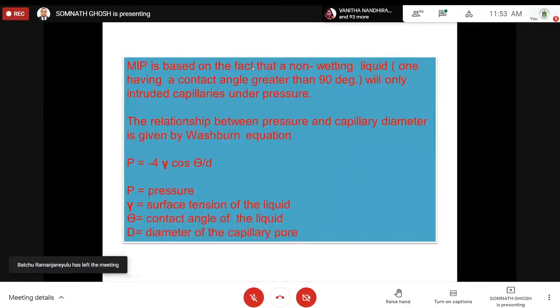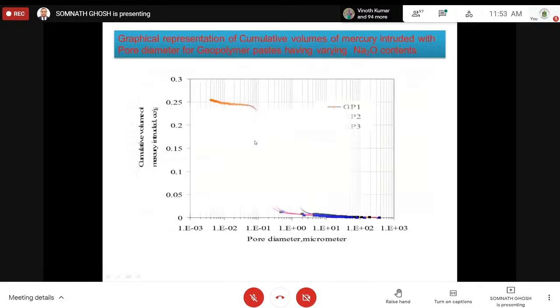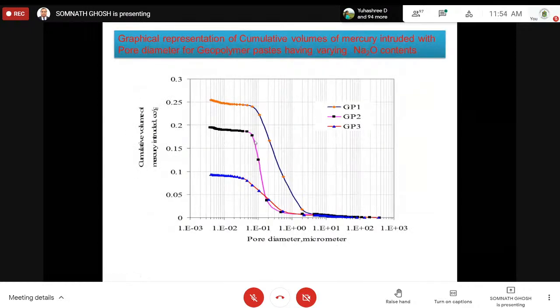Okay, it is based on the fact that a non-wetting liquid, mercury, one having contact angle greater than 90 degrees, will only intrude capillaries under pressure. And there are relationships to which pressure, contact angle, diameter of the capillary pore, all these things can be related. Right? Very easy. But the only thing that you have to be careful about is that at the end of the test, you will get a graph like this. In the computer, it will come like this, right?